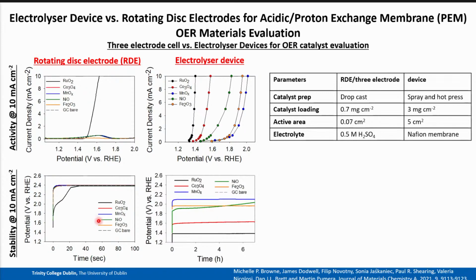So if anybody was doing these studies on these materials in a research lab, you would totally omit these studies from any further investigation. But in the electrolyzer device for the stability tests, these materials are all quite stable up to a period of 7 hours, except for the nickel oxide. But that's understandable because you will always have some materials that perform worse than others. So based on these results, I would say that the rotating disc electrode does not show us the correct results that you will get in an electrolyzer device.